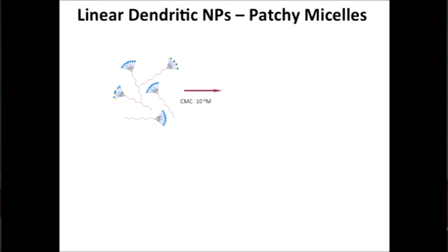But the problem here is that when the ligand is presented, we can't really control whether or not it's presented in a cluster. So we move to a block copolymer in which the hydrophobic block is a polypeptide that is hydrophobic, and the hydrophilic part is actually this highly branched molecule, a dendrimer. So we refer to these as linear dendritic block copolymers. And at the very ends of these branched dendrimers, we have the short polyethylene oxide blocks that are very water soluble and neutral. And to that, we can attach ligands if we want.